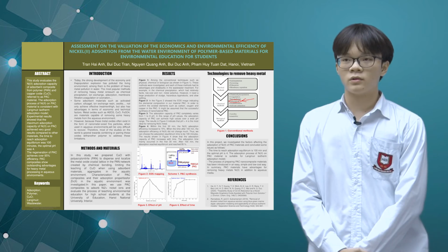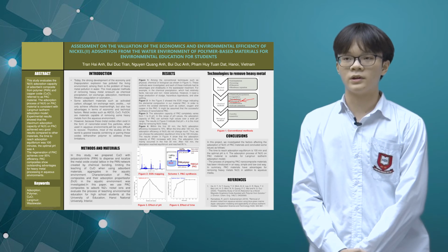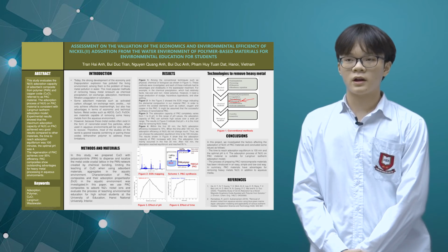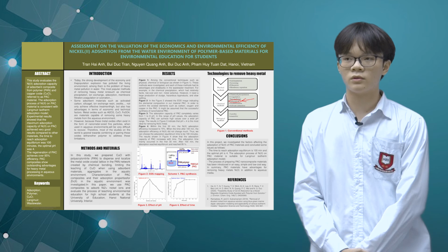In this project, we investigated the factors affecting the adsorption of nickel on PAC material and concluded some issues as follows. The time to reach adsorption equilibrium is 100 minutes and the optimal pH is 4. The adsorption process of nickel on PAC material is suitable for the Langmuir isotherm adsorption model.